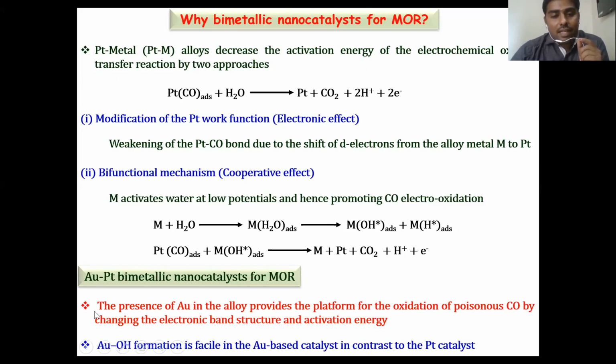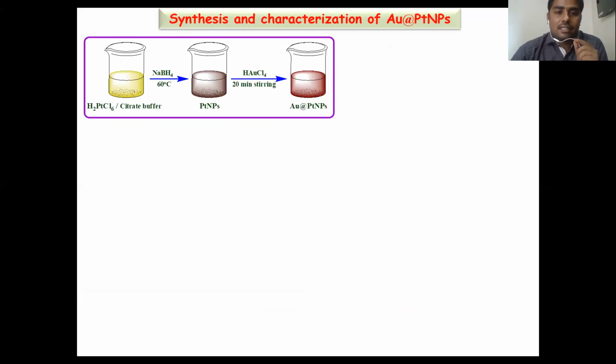Here, the metal activates water at low potentials. As we discussed already, platinum does so only above 0.4 volt. So if we combine it with a metal, it reduces the potential, and we may get metal water activation below 0.4 volt, and hence it promotes CO electrooxidation. When combining gold with platinum as a bimetallic catalyst, the presence of gold in the alloy provides a platform for the oxidation of poisonous CO by changing the electronic band structure and activation energy. The AuOH formation is facile in the Au-based catalyst in contrast to the platinum catalyst.